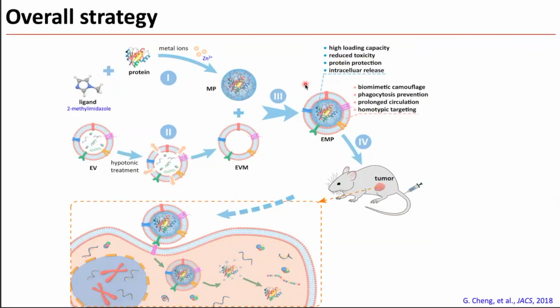And then to improve the systemic circulation time, minimize phagocytosis and provide targeting, what we do is we use EV membrane to envelop these nanoparticles. In this particular case, the extracellular vesicles we use are derived from the same cells we used to generate this tumor. So we collect those vesicles, we remove the internal contents and only harvest the membrane, and then we use the membrane to envelop the protein.